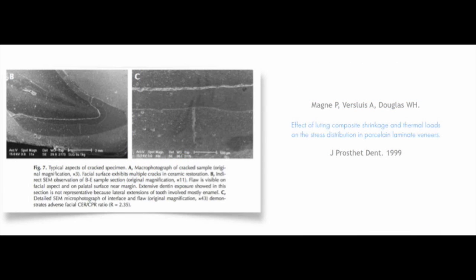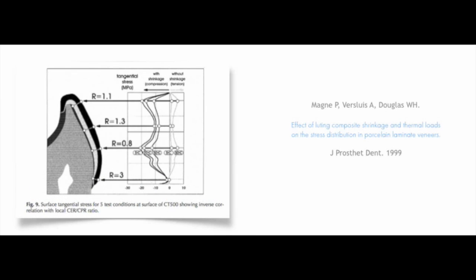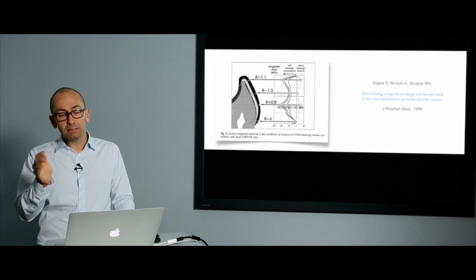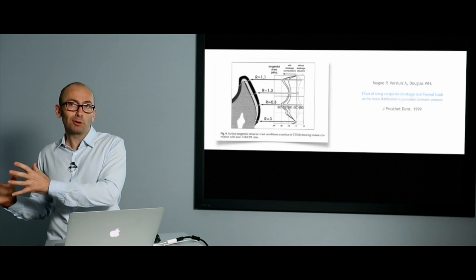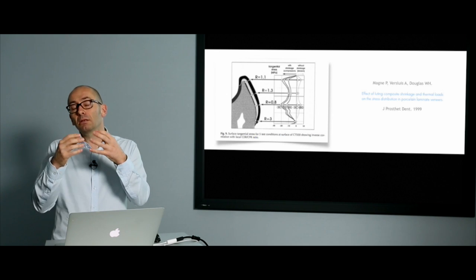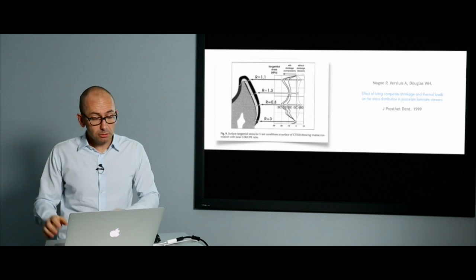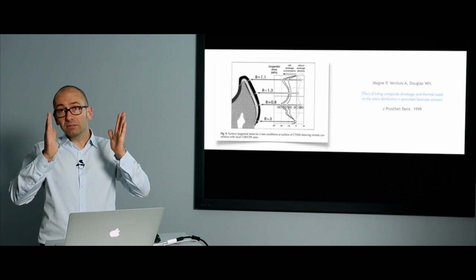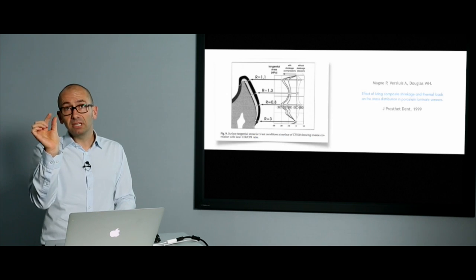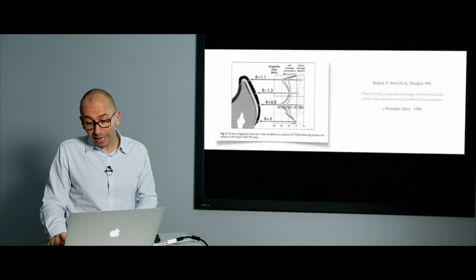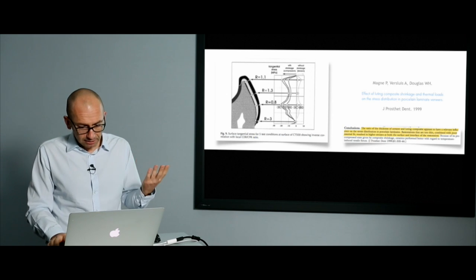Let's take a look at this other very famous study of Pascal Magne, done in 1999, and it's a comparison between the thickness of the prosthetic piece of the ceramic and the thickness of the luting cement and the tension between both. And it clearly indicates that as soon as your veneer is thicker, maybe 2 times thicker, 3 times thicker, so you have a ratio of 3:1, for example, you are in a security zone because you won't have any tension, because the veneer will be more resistant than the tension induced by the cement. But as soon as the thickness of the cement is increasing, and especially when you have a very thin veneer, you've got so much tension that there is a risk for cracks producing inside of your ceramic. So just keep that in mind.